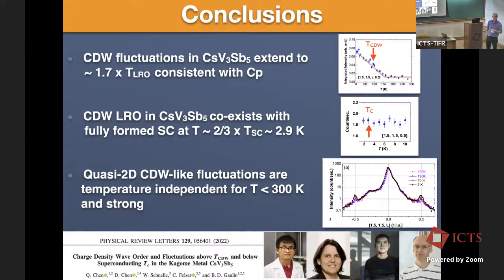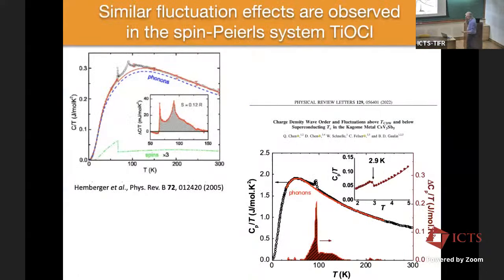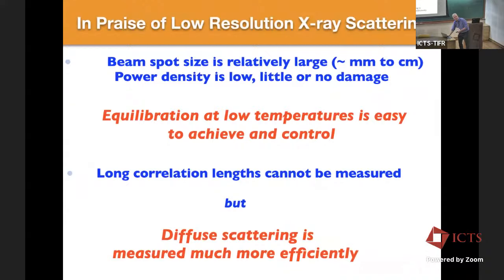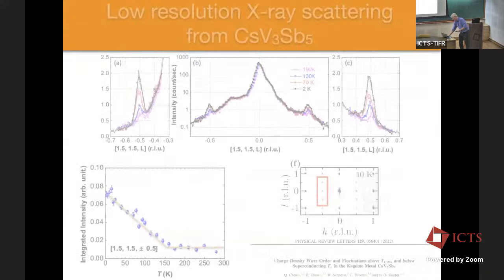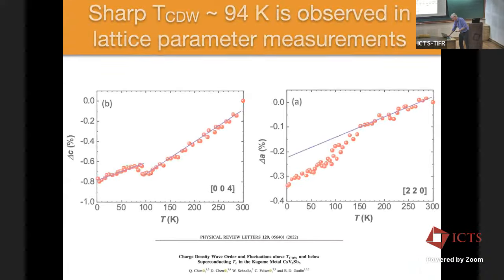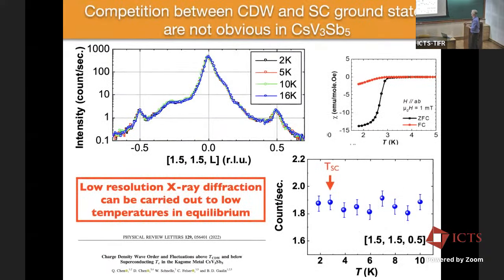Did you try to fit only the low temperature data after the CDW transition or something like that? Right. So at low temperatures, actually, you don't see it very well here, but below about 20 Kelvin, there's no temperature dependence to it at all. So that's what was shown here, or here, or here. You can see, this is from 16 Kelvin down, and everything just fits on top. So at temperatures of a few times TC, there's no temperature dependence at all, right?